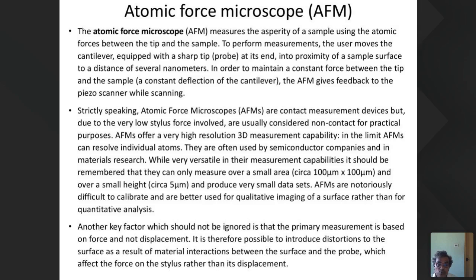To perform the measurements, the user moves the cantilever, equipped with a sharp probe tip at its end, into proximity of a sample surface to a distance of several nanometers. In order to maintain the constant force, the AFM gives feedback to the scanner while scanning. You are maintaining the constant force. Strictly speaking, AFMs are contact measurement devices, but due to the very low stylus force involved, they are usually considered non-contact. Though we say it is a contact, the force is very, very low, so practically we are taking it as a non-contact type.